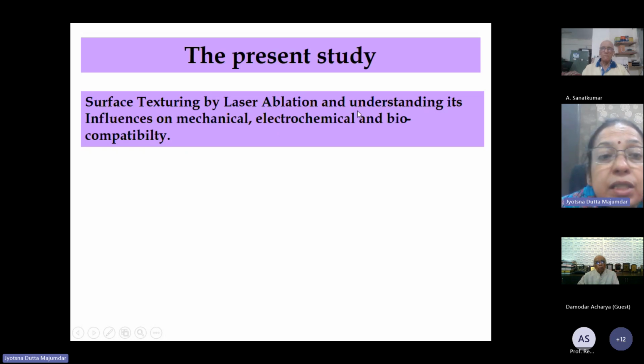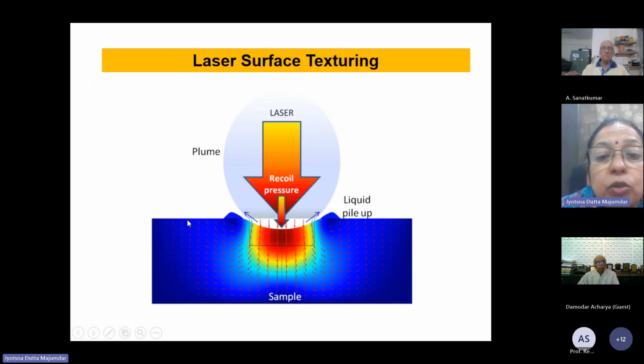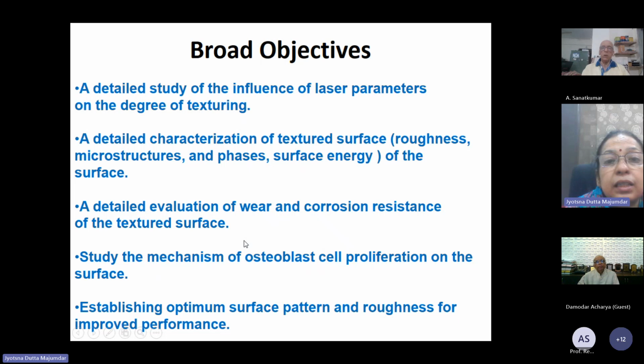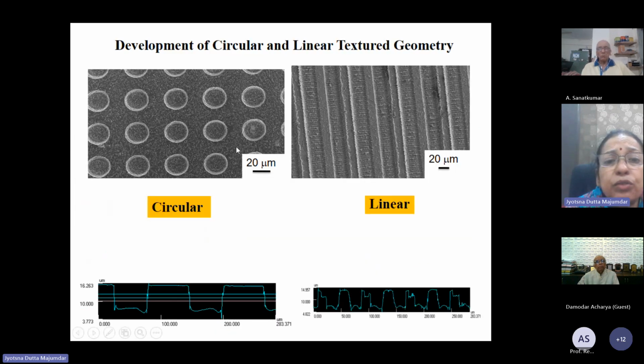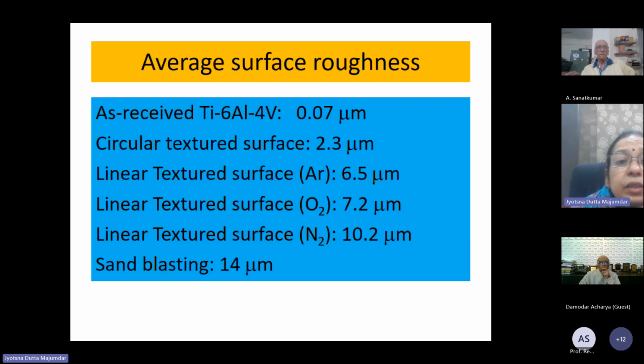The process is called laser surface texturing, to cause the periodic structuring. A high power nanosecond laser was employed on the surface to ablate the material, and subsequently rastered on the surface to cause texturing, and we tried to develop two different types of texture. One is a linear texture, another one is a circular texture. In one kind of texture, we remove the material spot by spot, with the diameter of each circle being 20 micron. Here again in a linear fashion, in both cases we covered almost 50% of the area which was textured, and 50% of the area was untextured. So this is a typical parameter.